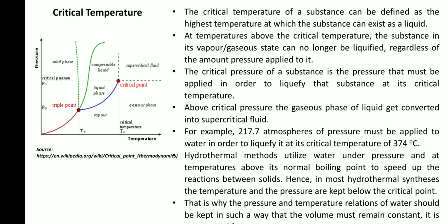If you are using a hydrothermal method, you should not go above 374 degrees centigrade or a pressure above 218 atmosphere. We have to always keep it lower than the critical temperature and critical pressure of water.